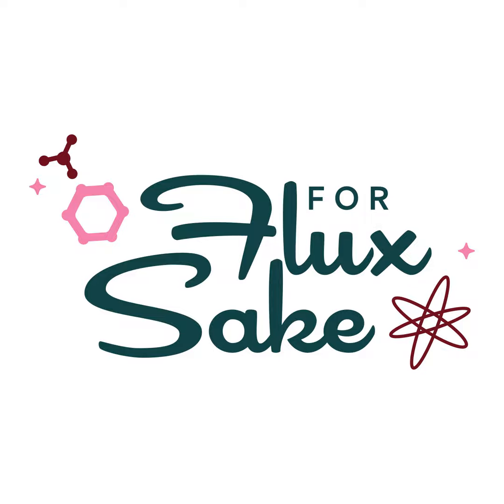Not to mention all the residual stuff that stays in your kiln. You might want to do just one reduction firing in your electric kiln, but then what residual material stays in there that you can't scrub out — it's fused on. We once installed a kiln outside just to do a burnout firing. We took one of our junk kilns outside, and after the firing the entire inside of the kiln was black. The clean-out was okay — we just refired it hotter and all the residual carbon bonded with oxygen, turned to carbon dioxide, and went away.